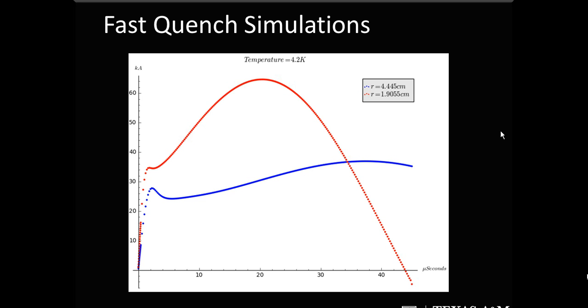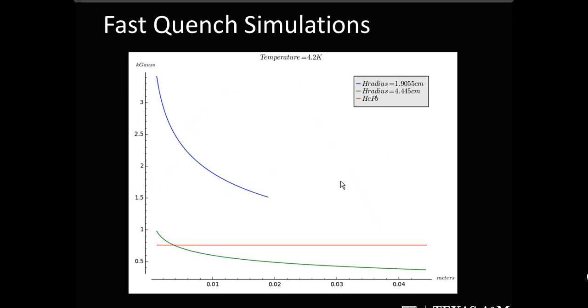You can see here we looked at a large radius sample and a small radius sample. With the small radius sample we can drive quite a bit more current through the magnetic coils than we can with the large radius sample. We can take that current and calculate our maximum magnetic field. So you see for a smaller sample of 2 centimeter radius, the magnetic field is well above the quenching field for lead out to the maximum radius of the sample, and with a larger sample our magnetic field falls quickly below the critical field at larger radius.